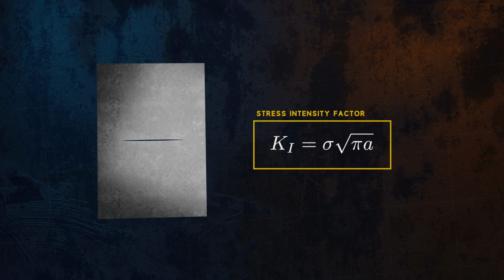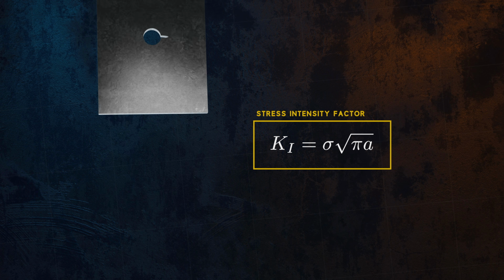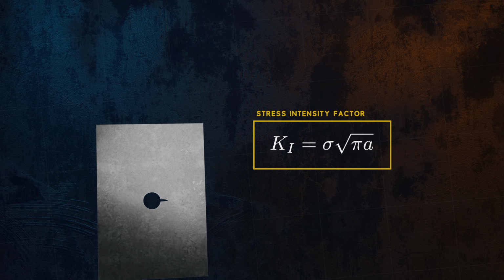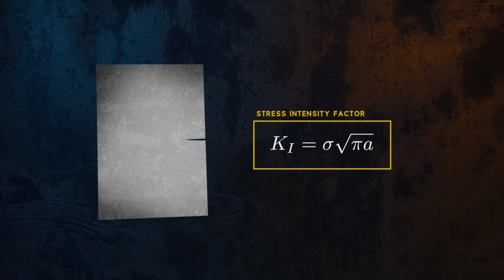This equation is valid for a through-thickness crack in an infinite plate, far from any edges, but real structures have finite dimensions, and cracks can take many different forms. A crack could have started at a hole, or be located on an edge, for example. These configurations are captured by a geometry factor Y, which scales the stress intensity factor up or down accordingly.